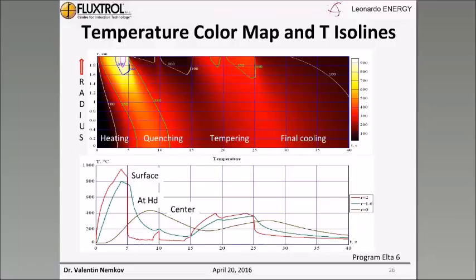Pay attention that the tempering time is very short, only 8 seconds, the same as we have for quenching time. And at the same time, we provide very uniform temperature distribution in the part. That's partially due to the fact that we don't cool the part completely during quenching. Some residual temperature, about 200 C, remains in the center and supports heating in the tempering stage. Here we have the distribution of the temperature on the surface, in the center, and at the depth of desired hardness. We can see here that the temperature of the center is more than 200 when the part is moved to the tempering stage.